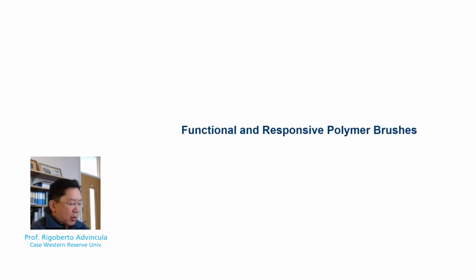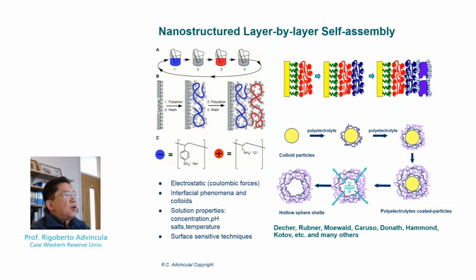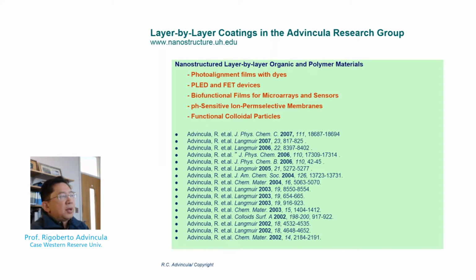Now, let's look at some of our work on functional and responsive polymer brushes by combination with layer by layer polyelectrolyte macroinitiators. So as I mentioned, the use of polyelectrolytes to modify surfaces with charged particles or polyelectrolytes can be achieved by alternating the deposition of, let's say, a negatively charged polyelectrolyte and a positively charged polyelectrolyte. These can be done on a flat surface or a particle surface, as shown here. One can achieve, in fact, a hollow shell configuration, let's say in this diagram, by removing the particle. And this has been done by many, many groups through the years and demonstrated in particles and surface substrates as well. We have done a lot of work in this field through the years.